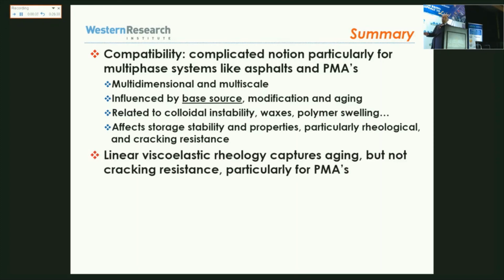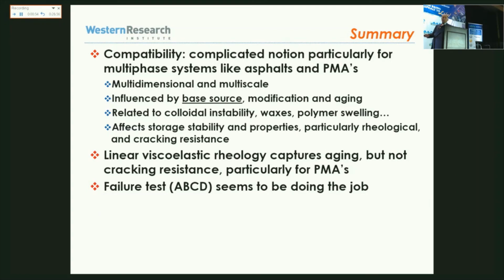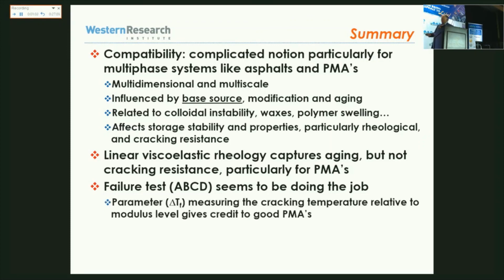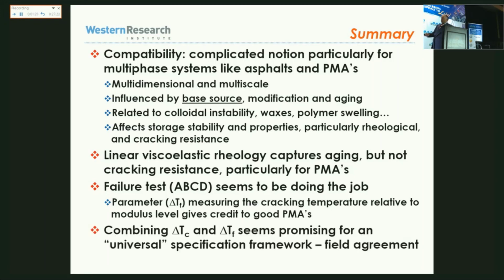Linear viscoelastic rheology captures aging very well. And that's the case for the global parameter, delta TC, but even G star divided by sine delta. So pretty much all of them, G star does. But it does not capture cracking resistance, particularly for polymer modified asphalt. Failure tests seem to do a good job, and we have ABCD, which is available. Maybe not the best test on earth, but that's the one which is available. The parameter delta TF measures the cracking temperature relative to modulus, and it seems to be giving good credit for PMAs and giving a logical ranking. Combining delta TC and delta TF seems promising for a universal specification framework, and a lot of this has been validated in our study. Of course, it's not the end of the story, because although it's a wide study, it's still limited. So more work is needed, but I think we're getting there.